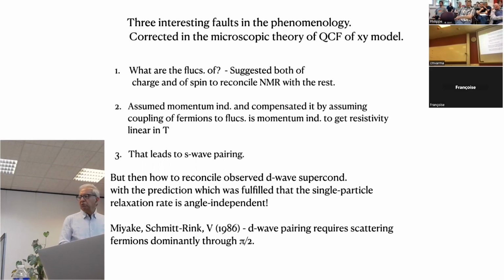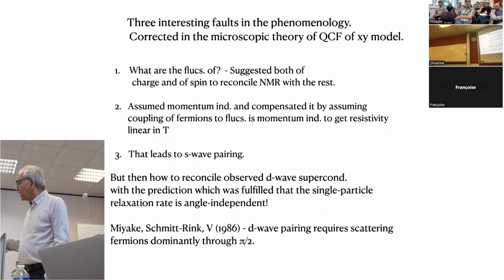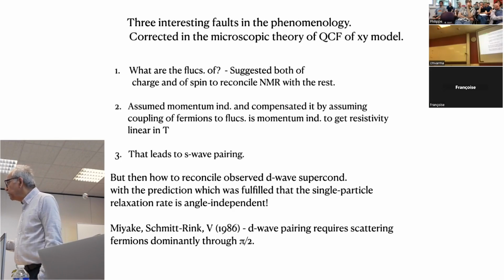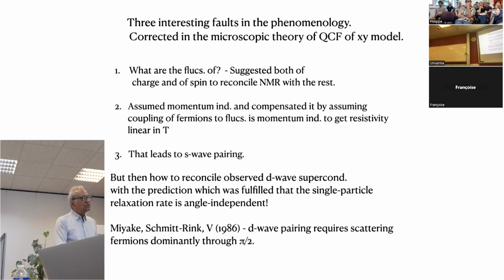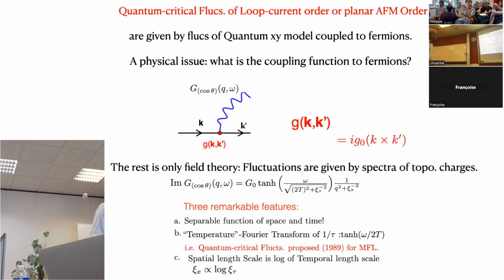Okay? We assumed momentum independence of the fluctuation and compensated it by assuming that the coupling to fermions is also momentum independent, okay, to get various properties. But this led to the prediction that the single particle scattering rate is angle independent, which indeed it is, but with my friends Miyake and Schmitt-Rink, I've proven before the high TC games began that D-wave pairing requires scattering by 90 degrees. So we predicted in that paper it should be S-wave, because we expected the single particle scattering rate to be angle independent. So there is this big problem. How to reconcile observed D-wave superconductivity with this. Okay? Now,